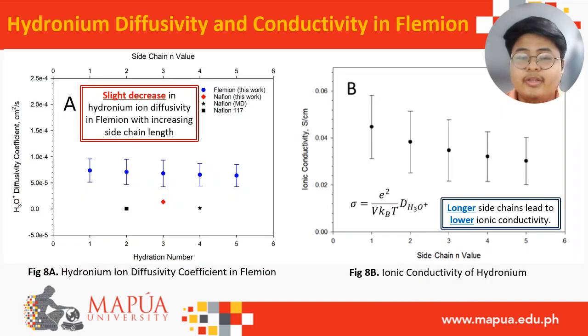Now, when considering the hydronium diffusivity, we have determined that there is a very slight decrease in hydronium ion diffusivity in Flemion with increasing side chain length, as seen in figure 8a. This is explained by the increase in polymer domain due to the free volume. This will be further expounded on in the next slide. As for the conductivity, there is a decrease. Longer side chains lead to lower ionic conductivity due to the decrease in aqueous domain.